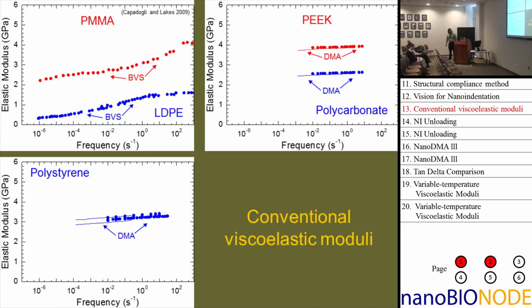So here's a set of materials that I started to work with, and these are all the conventional viscoelastic moduli. The PMMA and low density polyethylene were tested using broadband viscoelastic spectroscopy in Professor Lakes' lab at the University of Wisconsin. I got pieces of those materials from that study. Then the polyether ether ketone, polycarbonate, and polystyrene were materials that I acquired, and I did a conventional single cantilever test using a standard DMA setup.